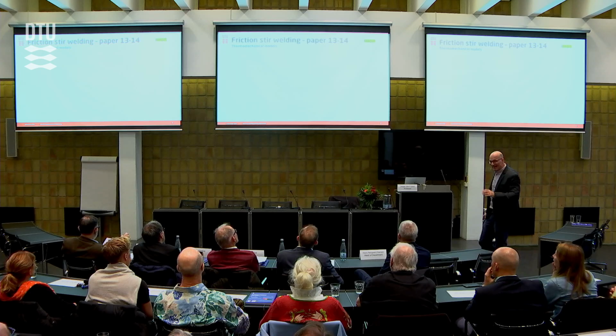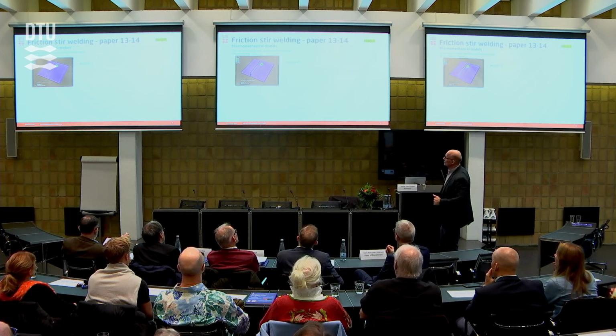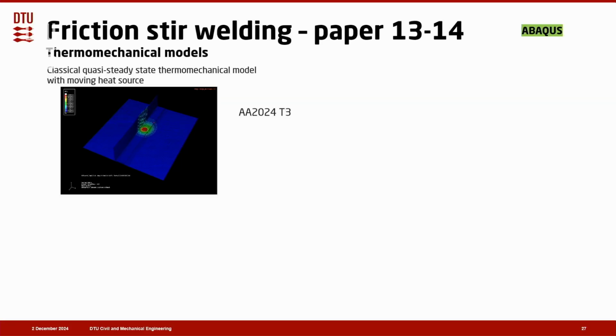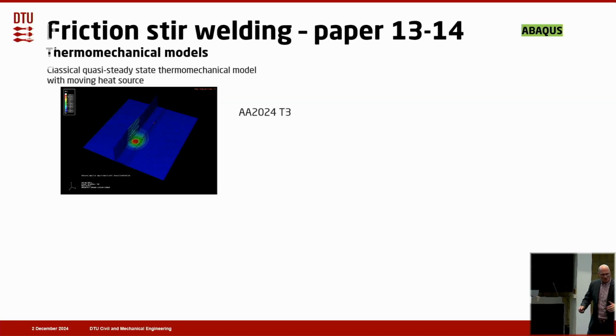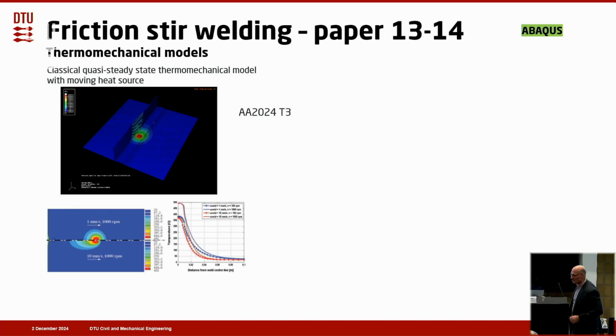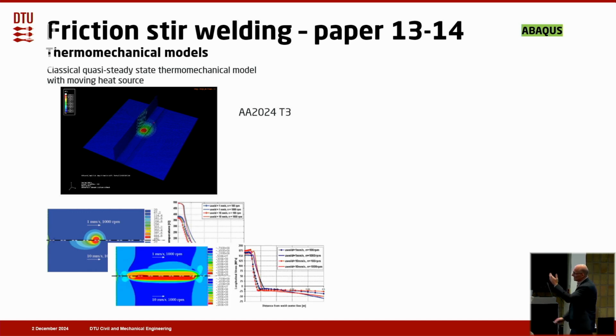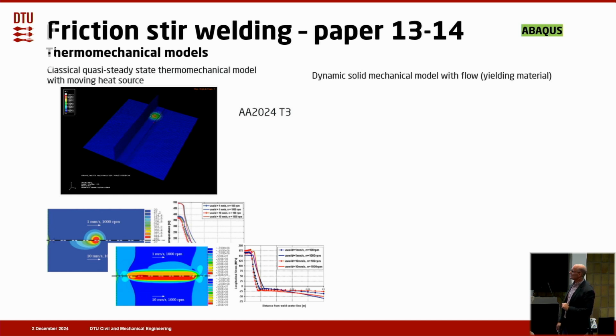Then we went to thermomechanical models. This is a classical quasi-steady state thermomechanical model with a moving heat source. So this is quite standard in welding, you could say. But the trick here is actually to find the heat source, really to calibrate it. So with this, we could make parameter variations where we varied the welding velocity as well as the rotational velocity. We could look at temperature fields. This is what you see here. And we could also look at the longitudinal residual stresses as a function of the choice of these process parameters.